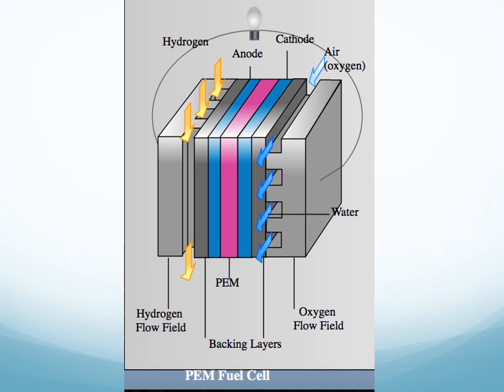One type operates at high temperatures, such as temperatures up to 200 degrees Celsius, and the other operates at temperatures of 80 to 100 degrees Celsius. Low-temperature PEM fuel cells use water-based electrolytes, while high-temperature fuel cells use a mineral acid-based electrolyte. High-temperature fuel cells can tolerate CO impurities better than low-temperature PEM fuel cells. High-temperature fuel cells can handle impurities in the hydrogen feed of up to 1 to 5% by volume, while low-temperature fuel cells can only handle impurities of up to 50 parts per million.